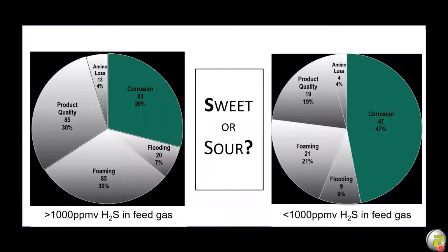So as far as the way these things lined out, we did try and separate, we've got one for refineries. We do work in LNG facilities, syngas facilities, carbon capture, but this is strictly from the gas treating focus of our database. And the one on the left is processes with greater than 1,000 ppm of H2S in the feed gas, and the one on the right is less than 1,000. So we're calling the one on the right sweet gas. Now, obviously there's H2S in it, and you'd consider it sour gas, but we've just used 1,000 ppm as our